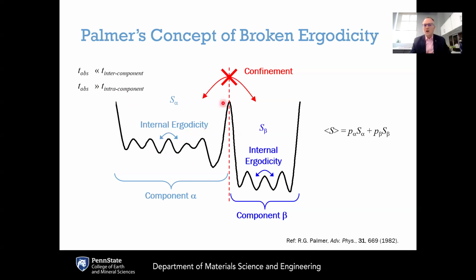The second assumption that Palmer makes is called confinement. Confinement implies that the observation timescale is much less than the timescale required for intercomponent transitions. In other words, the timescale that's required to transition between components is so much longer than our observation timescale that it effectively doesn't happen. And so that is the second condition of confinement. So basically, Palmer's assuming a hierarchy of timescales: really fast timescales for transitions within a component, an intermediate timescale, which is our observation timescale, and then a much longer timescale for intercomponent transitions.